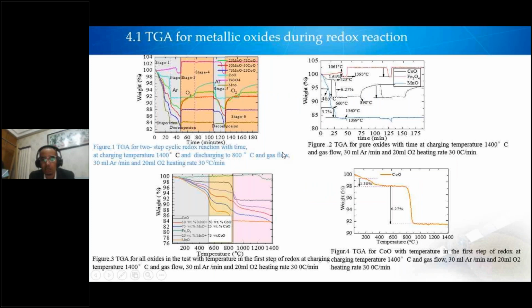Thermogravimetric analysis for the composition of the oxides. So we see that in the first two cycles, redox reaction has gone. As you see, in the first stage we see evaporation. In the second stage decomposition starts, and then reoxidation is ongoing in stage 3. In stage 4, once again decomposition happens. So the situation ran for 2 cyclic redox reactions, and then among these, which is going to be more stable.